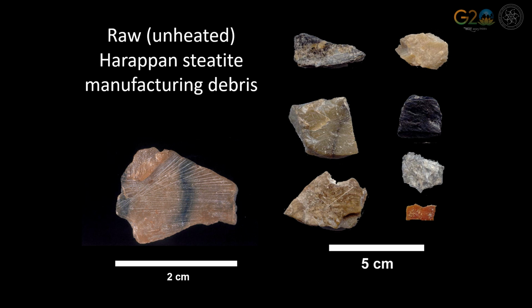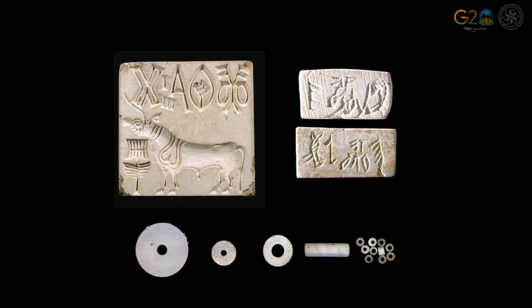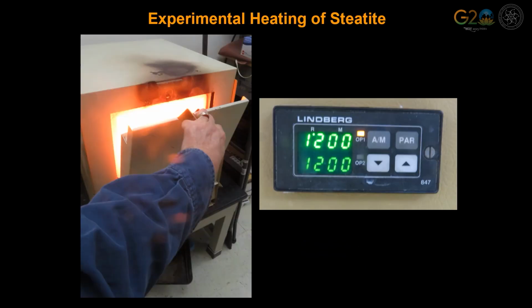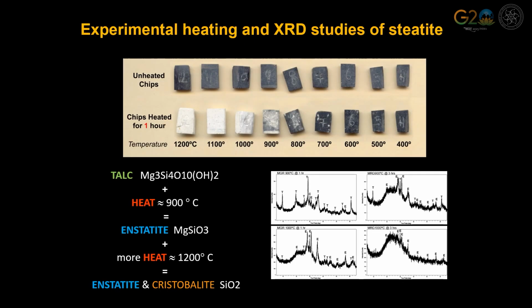Recall the highly varied appearances of the raw steatite production debris fragments from Harappa. Now, compare those to the outward appearances of the vast majority of Indus artifacts composed of steatite. The difference is striking. Most Indus steatite artifacts have a white or off-white appearance. This is because they have been heat treated. Over the years, we have conducted a great many experimental heating studies involving steatite. We have found that subjecting steatite to temperatures between 900 to 1200 degrees Celsius significantly alters the appearance, hardness, and mineralogy of the stone.